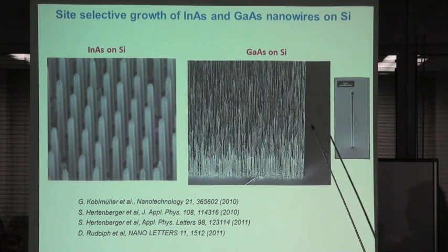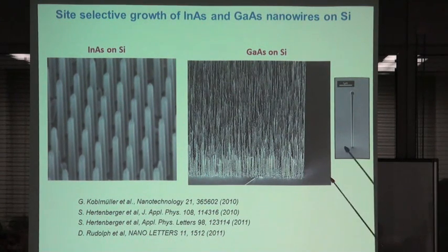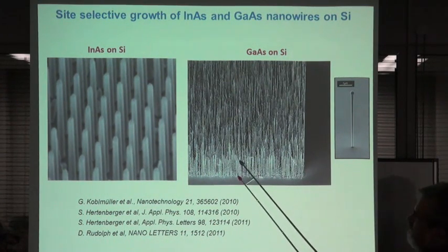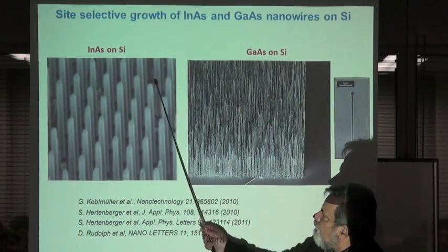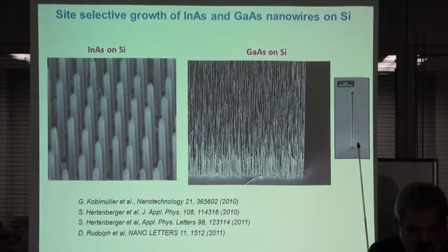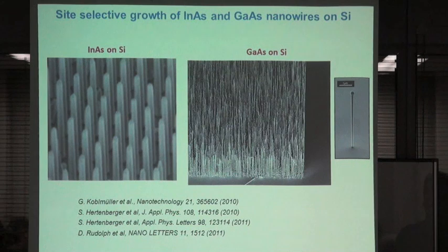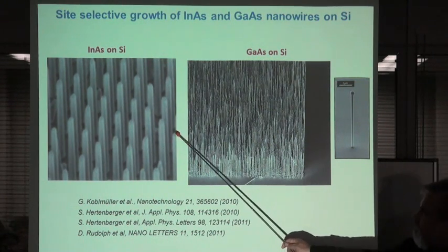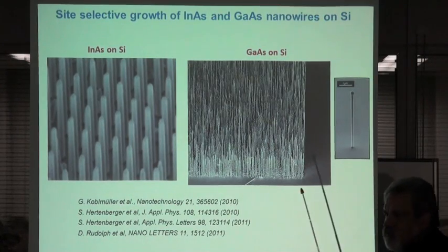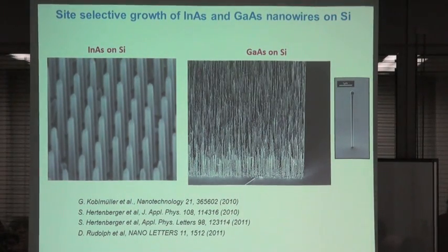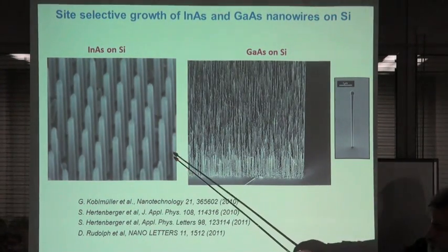So at the moment we are still working with the growth conditions to get a high yield, because one of the goals is not working maybe with single wires, but making them on silicon. They are in the hole. You have maybe a doped silicon substrate. This is a back contact. Then you have the nanowire. Indium arsenide is N-type. So if you then have a top electrode here, depending on whether you use a P-type substrate, you have immediately a PN junction for many of these wires.